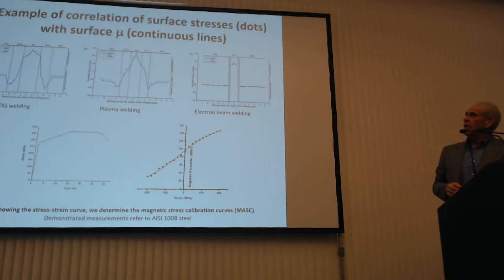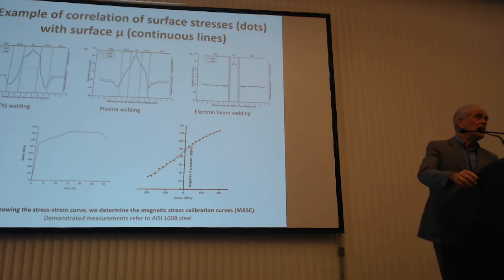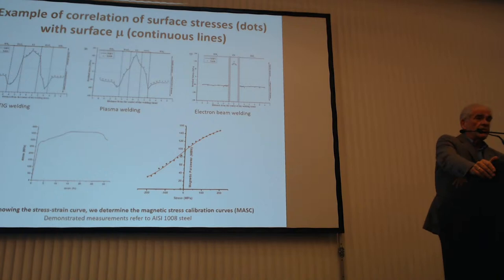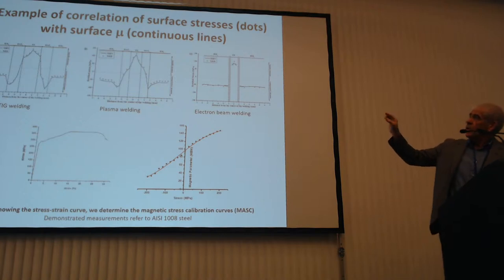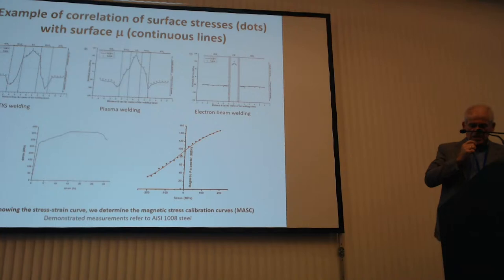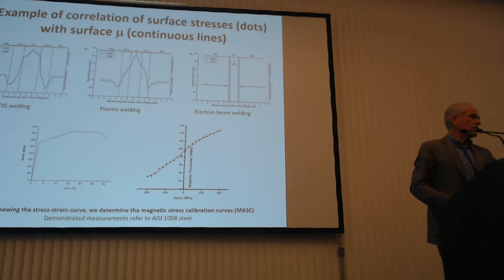And what we have computed is depicted very well, I think, in this graph. You can see that these graphs concern the distribution of residual stress measurements demonstrated by points. You see, there are some points on these three graphs representing the welding area, so the fusion zone, the heat affected zones, and the dots represent the actual residual stress measurements by either X-rays for the surface or by neutron diffraction for the bulk.